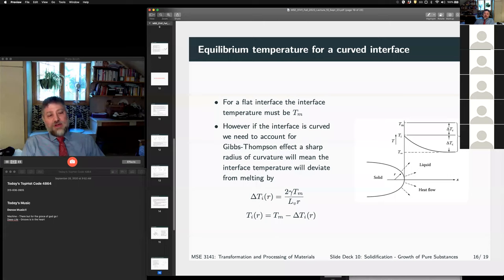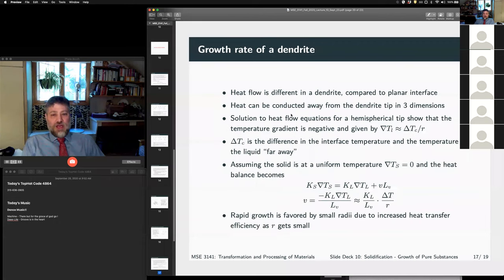So the total undercooling is given by this delta T naught, right? The undercooling that we're growing into is this delta TC, right? So the tip at this interface is different than the tip back here, right? Okay. So because of this, heat flow is different in the dendrite compared to a planar interface, right?